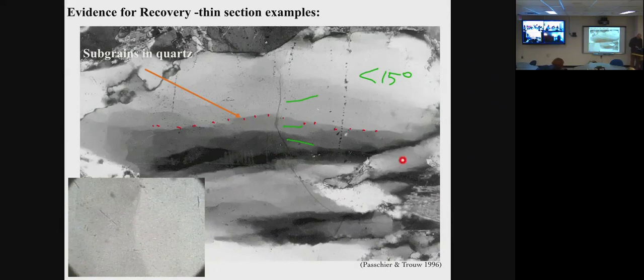This crystal here and this crystal here, your eye sees the boundary very sharply as a grain boundary. That means that optically, this crystal has an optical axis greater than 15 degrees to this quartz crystal. So your eye will see subgrain boundaries if the angle difference is subtle, within 15 degrees, or greater than 15 degrees, your eye will see it as a grain boundary. Two quartz next to each other with a sharp line means the optical axes are very, very different. Okay?